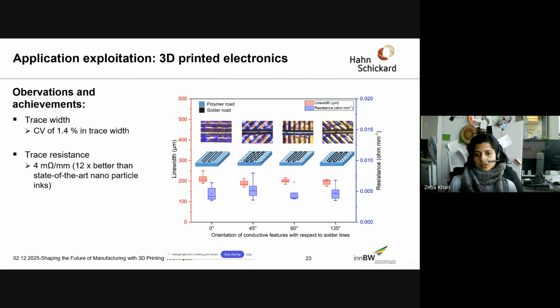individual droplet deposition, and you can see how well the traces have fused to form this very smooth line, wherein you see the standard deviation is also not too high for the trace width. Of course, one would expect the orientation to have an influence on the trace width. However, no significant variation was visible. Same for resistance, and it was possible to have resistance which was 12 times better than the nanoparticle inks from the state of the art.